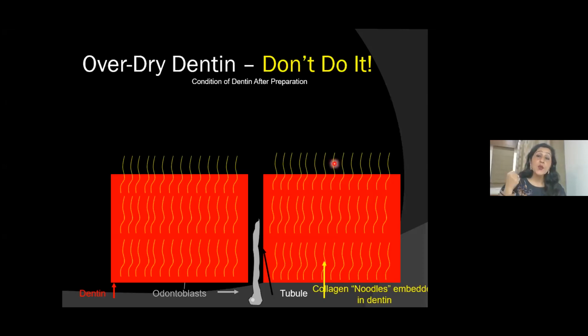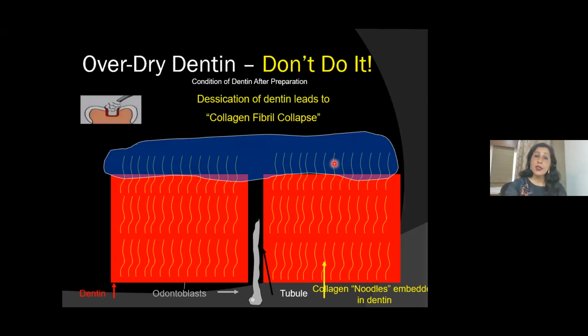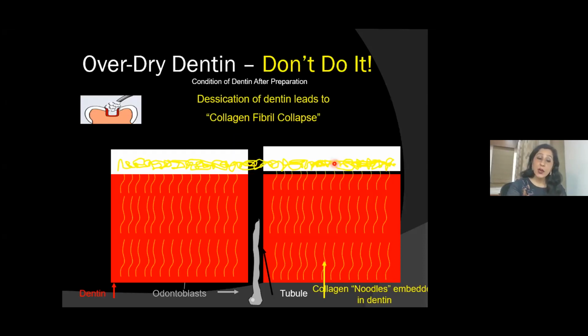When you blow air onto enamel, not much harm is imparted to enamel. But what happens on dentine? Desiccation of dentine leads to collagen fibril collapse. This is what happens when you blow hard on dentine. The collagen fibrils collapse and stick together. Once this agglutination occurs, these fibrils serve as a barrier against penetration of primer or adhesive. When adhesives cannot reach the exposed tubules, they fail to seal, and again, this will lead to post-operative sensitivity.